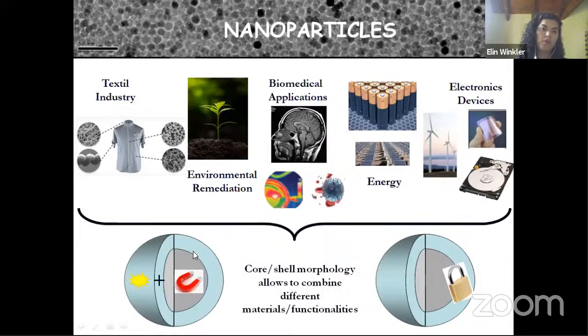So in that way, we can combine two different functionalities. For example, here, like in a cartoon, I draw a magnetic nanoparticle, which is encapsulated with a material with optical properties. So we can use that for magnetic application and also for imaging. Also, when we fabricate core shell nanoparticles, it could be that at the interface the two materials are coupling, so the new material, the core shell nanoparticle, presents different properties than the parent components.